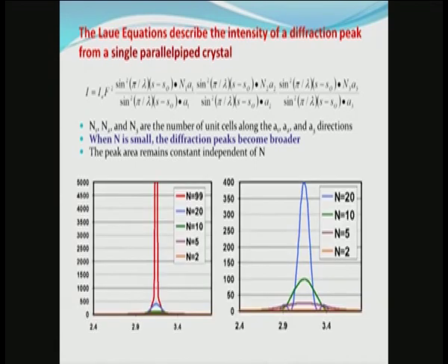What is shown now is the simulation of how the intensity of the peaks varies with the number of planes n as in the above equation. So, what you see here is that if n is equal to 5 for example, as shown in this graph, then the peak is really very broad. When n comes to 99 for example, you get a much sharper peak.